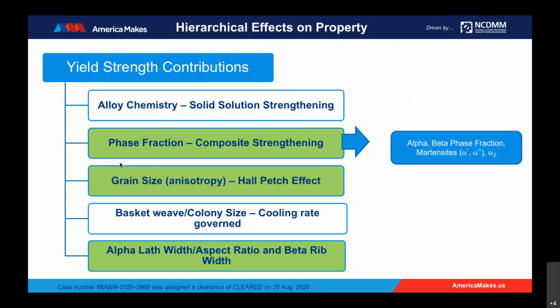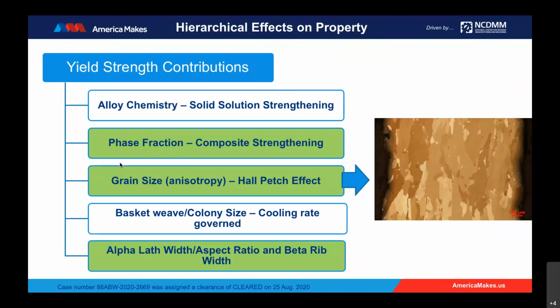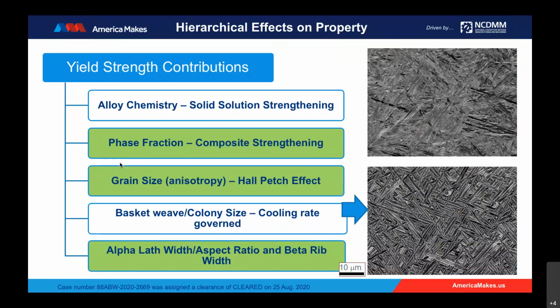Phase fractions, right? So when you do the particular heat treatments, the alpha and the beta phase fractions, along with the fast-cool martensitic and possibly alpha-2 phases, are of interest from the Ti-6-4 side. Grain sizes and grain anisotropy. So here the Hall-Petch effect comes into play. So the image that you can see here are very anisotropic grains, grown more elongated or columnar along the build direction. So that would change to have varied property along the vertical and the horizontal directions. And then taking one level deeper, we talk about this basket weave versus a colony microstructure in Ti alloys, which is really a dependency of the cooling rate.